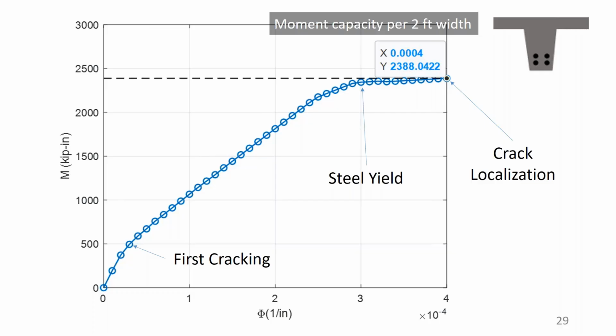And you can see some interesting things in the moment curvature relationship. For example, you can see first cracking all the way down here. And you can see the steel yield where it yielded, and eventually crack localization. So that means that under service conditions, the material is going to be operating in the strain hardening region, meaning the very dense, very fine cracking.